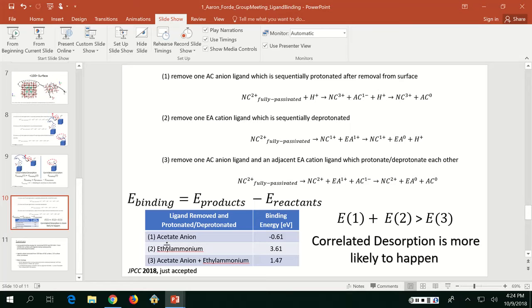So, the ethyl ammonium doesn't do any chemical bonding, so it is purely electrostatic. If you didn't know anything about it and were just trying to put an order of magnitude estimate on what you think the binding energy would be, it would be in the eV range. Another thing: is it the average binding energy or just one ethyl ammonium? Just one, so it's just from that site. So the binding energy is from that one site.